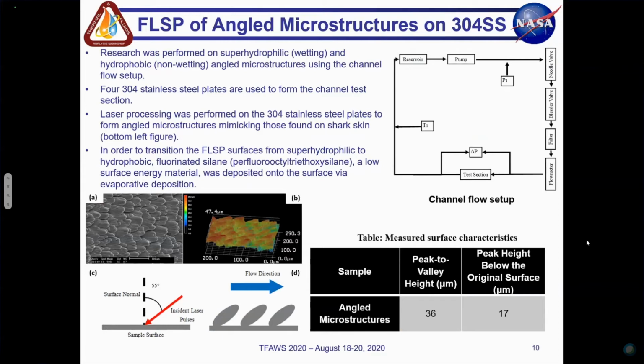So we took these smooth plates that we had processed. We processed them to get angled microstructures that were super hydrophilic to start, and then using a coating, we're able to make them hydrophobic, non-wetting, and use them in this channel flow setup. So we use 4 304 stainless steel plates to form the channel test section. You have 2 on the bottom that are 4 centimeters wide by 45 centimeters long, and the sides of the channel themselves were laser processed.